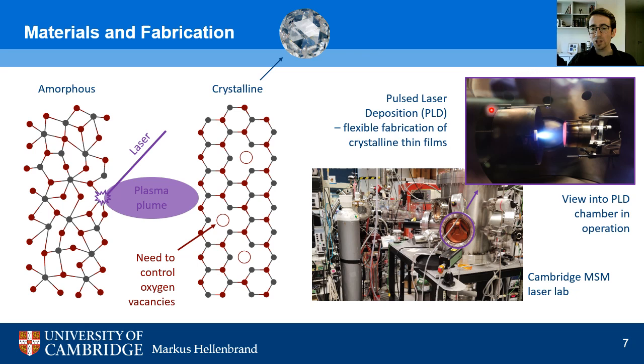And because the chamber is evacuated, this evaporated material can travel over to a substrate on a heater here. So you see the orange glow, which means it is at a very high temperature. And by controlling the conditions inside the vacuum chamber, so the pressure, the energy of the laser, the distance between the target and the substrate, and so on, we can make the atoms arrange themselves into a crystalline material.